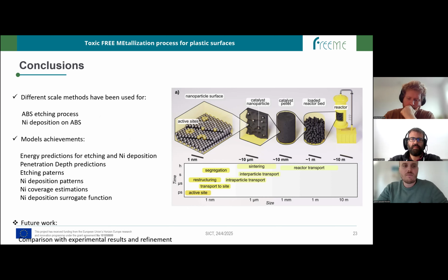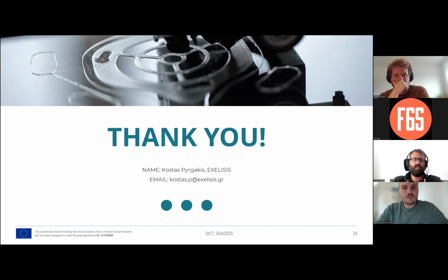And then just to recapitulate very shortly, we have used different scale methods for the ABS etching process and nickel deposition on ABS. That was the first objective, the deposition experiments that we wanted to investigate. Then we are able to do energy predictions for etching and also for nickel deposition. We also can have penetration depth predictions, etching patterns, nickel deposition patterns, and nickel coverage estimations. And finally, we have also been able to generate a nickel deposition surrogate function or model that we can plug into higher level models, such as CFD simulations. And that's all. Thank you so much for your attention.